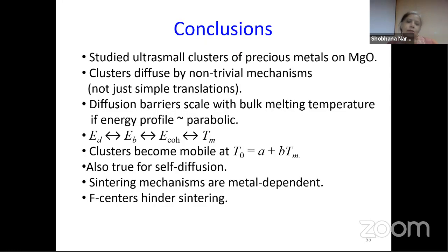So I'm done. So we've studied ultra small clusters of precious metals on MgO, and they diffuse by very non-trivial mechanisms like rolling and cartwheeling, etc. And I've shown you that the diffusion barriers scale with the bulk melting temperature if the energy profile is approximately parabolic. This was something that people didn't realize before our work. And I've justified why this happens. And I've also been able to explain this empirical result of the Huttig temperature where clusters become mobile for self-diffusion. The sintering mechanisms are metal dependent and F centers hinder sintering.